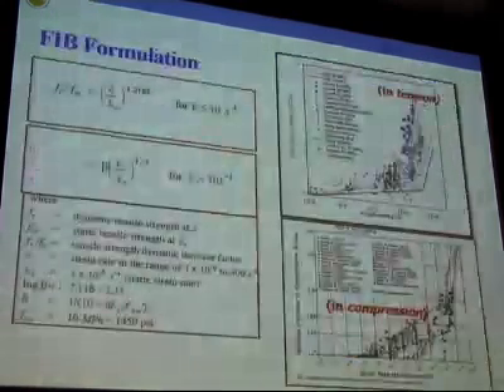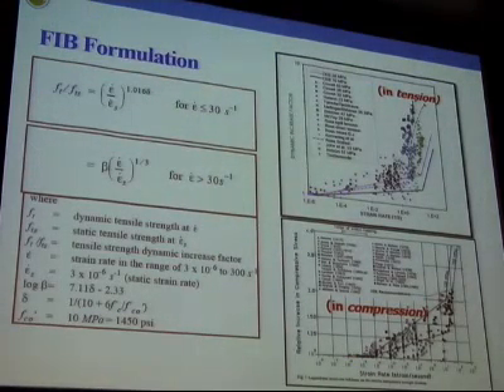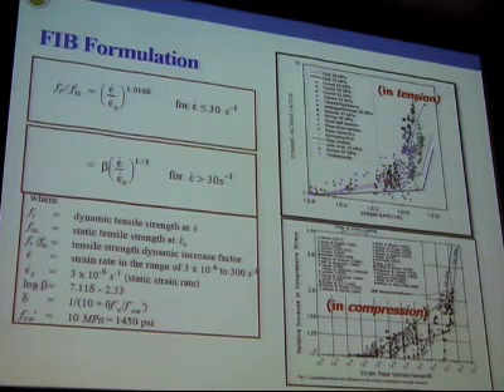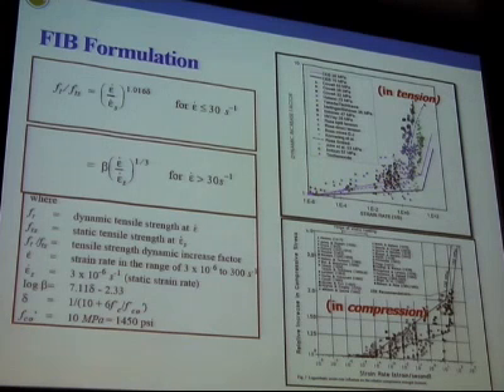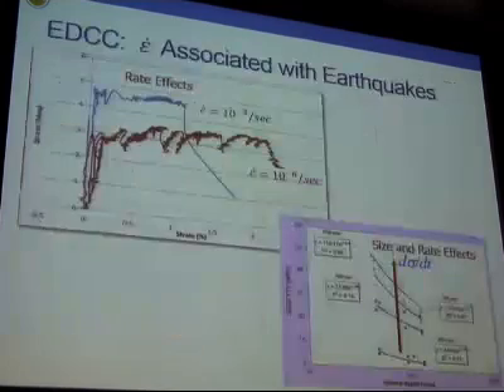Now, typically, what we do understand is that the materials are highly sensitive to rate, and this is a synopsis of hundreds of test studies that have been performed. You will notice that when I'm plotting a response versus strain rate, it performs in a bilinear manner. So you would have a knee in the curve here, and your earthquake loading is somewhere just before the knee or just after the knee, so just before it becomes highly sensitive. And there's been a fair bit of work done on these materials under high rates of loading.